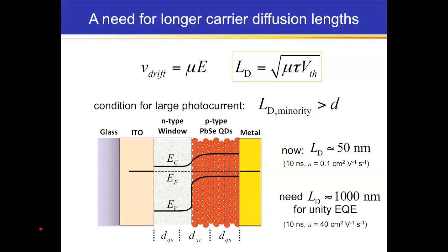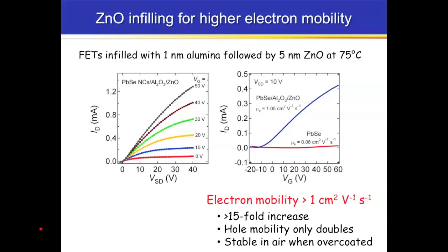What we need to do is to get to a carrier diffusion length closer to 1,000. To do that, we could use, say, 10 nanoseconds, but we need to boost the mobility to, say, about 40 in order to achieve that kind of diffusion length. And so there's a big effort in the field right now to increase mobilities to sort of that level. And I want to show you how we can do that or get close to that using this ALD approach.